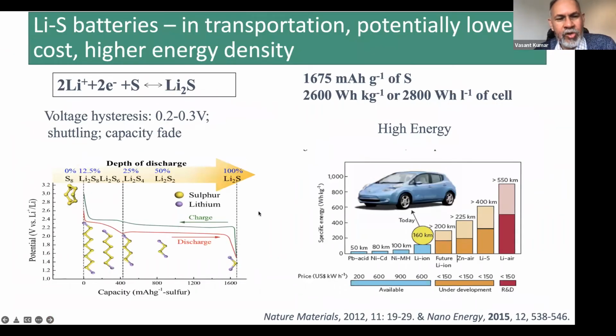But the chemistry is very complex. It looks very simple, lithium and sulfur, but sulfur is a crown molecule, and once it begins to dissolve in the organic solvent containing the lithium salt as electrolyte, it forms various polysulfides. They are polymeric in nature. They make the electrolyte quite viscous, and then the potential decreases, and it reaches a sort of steady state where other polysulfides form, with higher lithium content, and ultimately it forms Li2S2 and Li2S. These are not soluble or less soluble in the solvent, and they precipitate out. Both sulfur S8 and Li2S are highly insulating solids. So that's one problem.